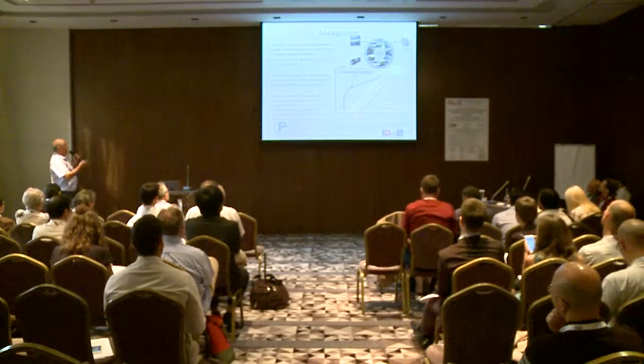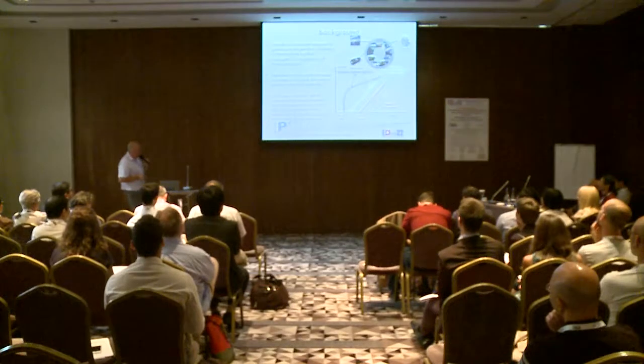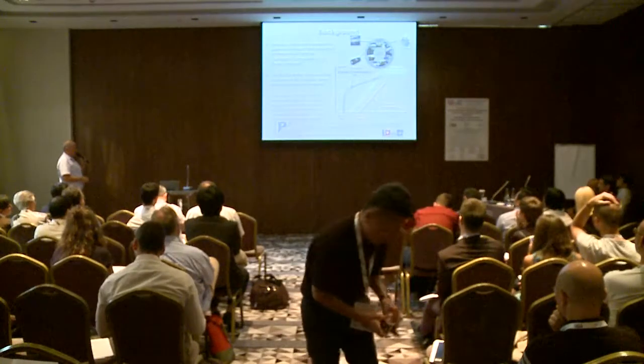As regards the background of this study, we initiated this type of experiments a couple of years ago within the framework of a so-called hydrogen-based economy, where you need information about the hydrogen compatibility of materials used for infrastructures of transport and storage of gaseous hydrogen. This issue is all the more complex if you take into account the presence of a crack-like defect in a structure submitted to cyclic loading, because it is well known that the presence of hydrogen in the surrounding environment can be a source of fatigue crack growth enhancement.